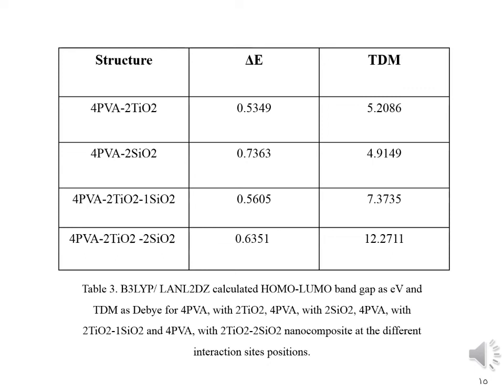Total dipole moment doesn't change significantly, where it becomes 5.2086 and 4.9149 Debye for polyvinyl alcohol to titanium dioxide and for polyvinyl alcohol to silicon dioxide respectively. The decreased values of HOMO-LUMO energy gap confirmed the ability of polyvinyl alcohol to titanium dioxide and polyvinyl alcohol to silicon dioxide structures to interact with other nanostructures. It is noted from the results that the band gap energy for polyvinyl alcohol to titanium dioxide is lower than that of polyvinyl alcohol to silicon dioxide, which confirms that the surface of polyvinyl alcohol to titanium dioxide is more reactive.